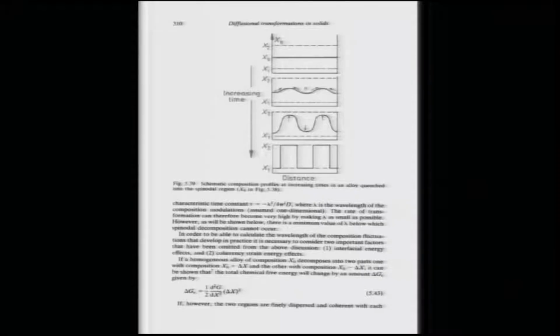So, therefore, the diffusion happens down the chemical potential gradient, but the way it takes place, it looks like it happens up the concentration gradient. A goes to the A rich region, B goes to the B rich region. So, that is why it is called compositional partitioning.